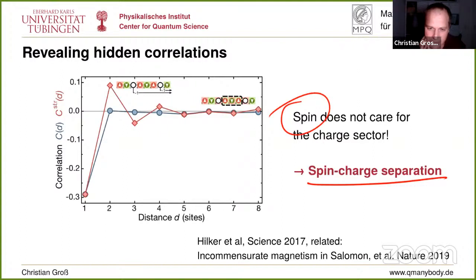And I think with the microscopes it is always a bit hard to compare the lattice temperature in the strongly correlated lattice systems to bulk systems and so on and so forth. But we are roughly at 0.1 TF, I think. Record temperatures in bulk systems cooled sympathetically are at 3 or 5%, so a factor 3 to 2 colder, by sympathetic cooling with a boson. So there's a hint that this works slightly better.